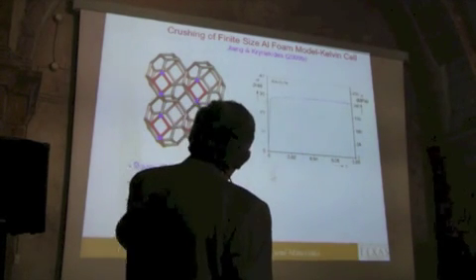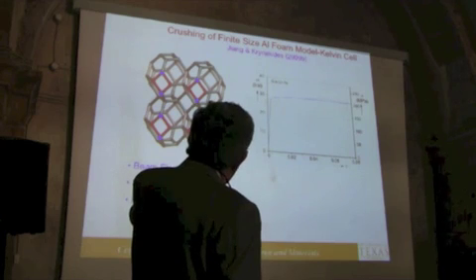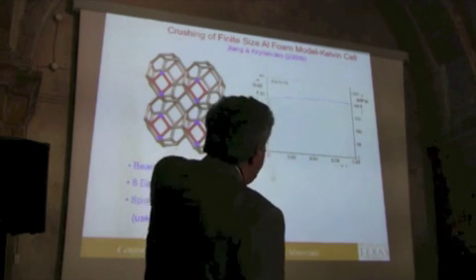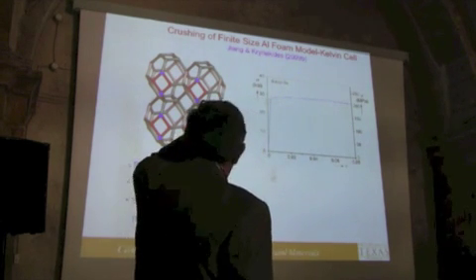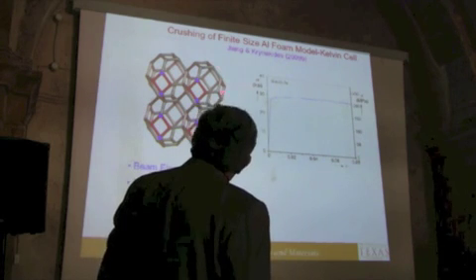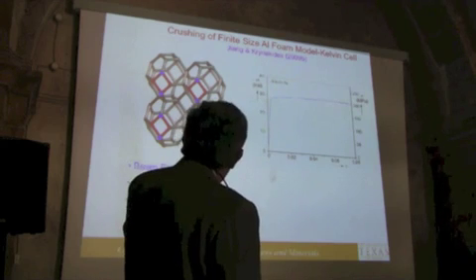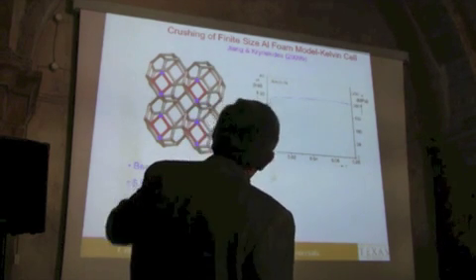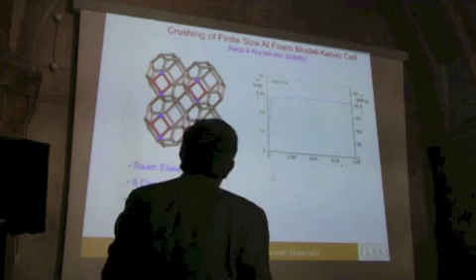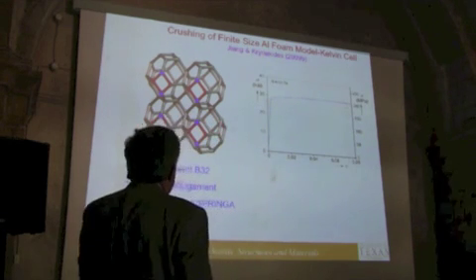The first approach that we took about 5 years ago was to model this, idealizing the geometry a little bit. We were helped by the fact that the volume of the cells doesn't change, it is monodispersed. So we idealized the microstructure like this. This is the Kelvin cell, but we introduce ingredients from what we measured. That means we have the correct density, we have some anisotropy, and the distribution of the material along the ligaments came from measurements that we made.